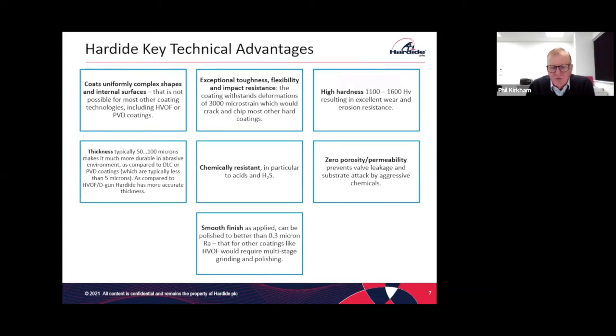As compared to other coatings, it's in the middle. There are very thin coatings like DLC, which is a diamond-like carbon coating, or again PVD. These are typically 5 microns thick. HVOF, D-gun, other types of tungsten carbide coatings tend to be very thick in the millimeter range. So we're in that middle range where really nobody else has a coating that will fit that gap.